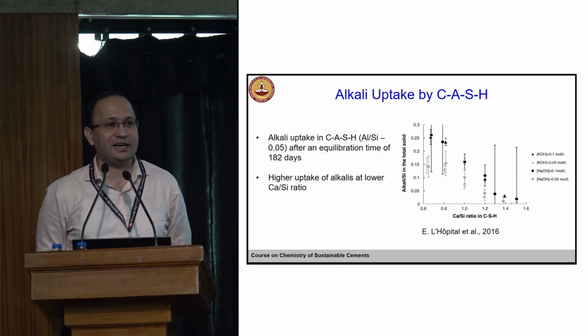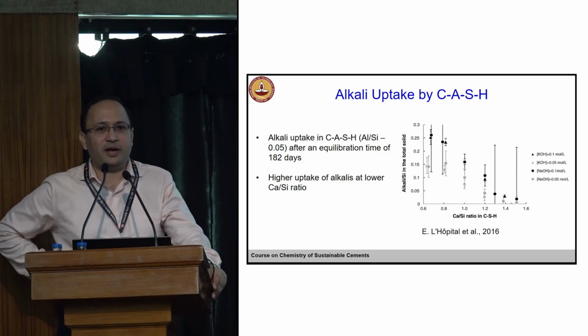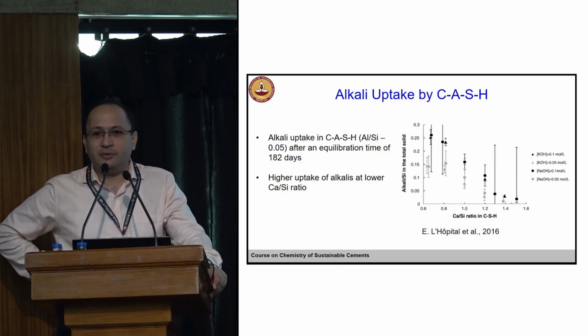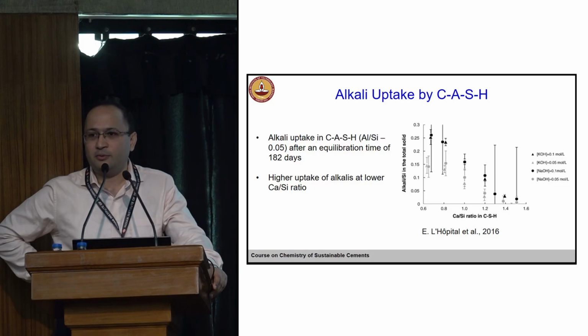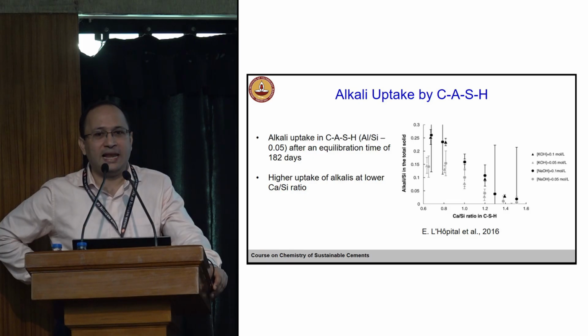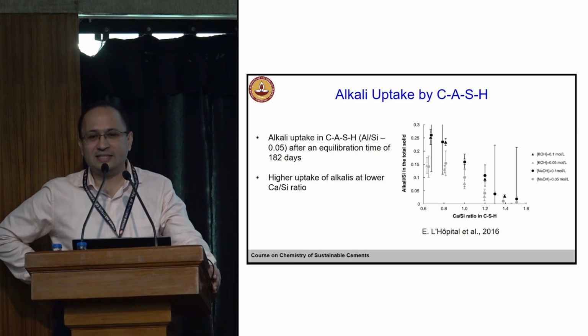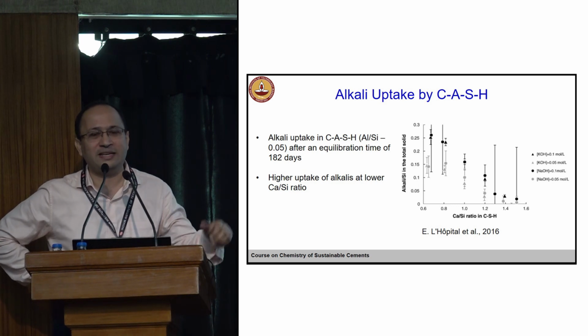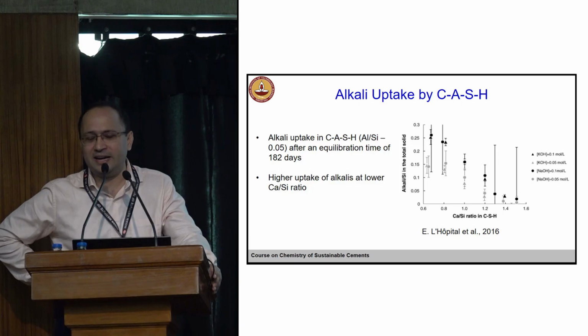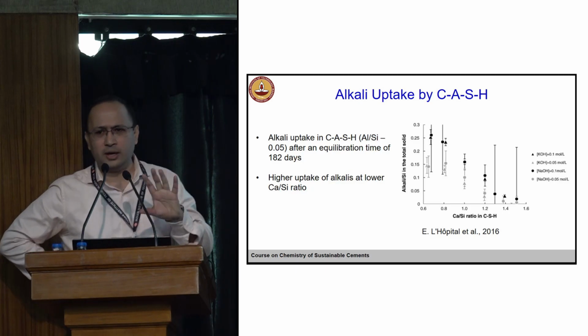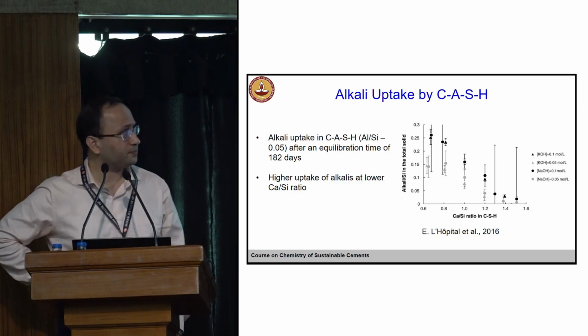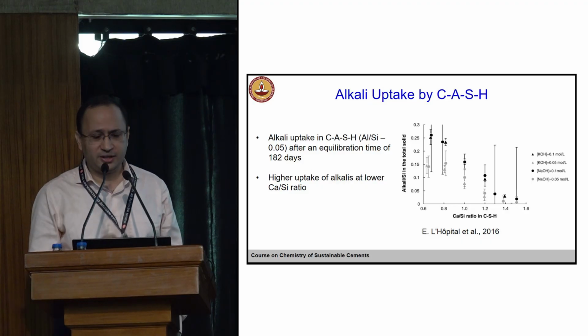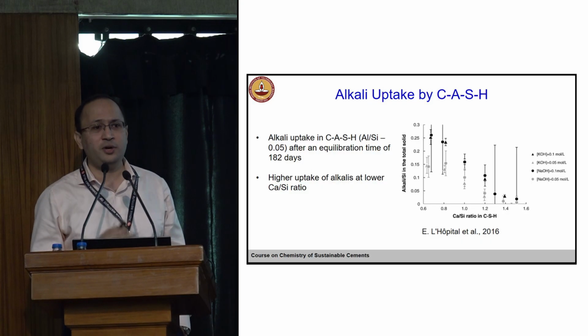For example, alkali silica reaction. Let's say in cases where you have reactive aggregates, now you have a pore solution which has high pH, and these aggregates will have a tendency to react and form alkali silica gel. Now, if you can somehow reduce the alkalinity of the pore solution, so alkalis are not freely available in the pore solution, they are bound by CASH, calcium aluminosilicate hydrate. That also reduces the susceptibility towards ASR. Anyway, we are not going to talk about that, but this has a consequence. So these are some of the changes you see in the structure of CSH, its binding capacity when you introduce SCMs.